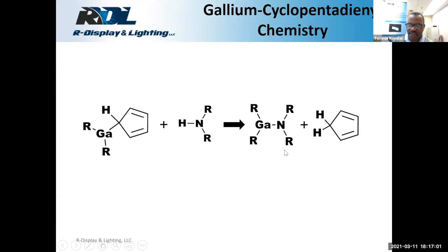In grad school, the interest evolved around using these materials as potential single source or single molecule precursors for preparing ultimately gallium nitride semiconductors. The problem is pyrolyzing these materials ultimately results in incorporating impurities in the microstructure of the gallium nitride semiconductor. So it's not a process that can be competitive with the standard MOCVD process, the bimolecular reaction between trimethylgallium and phosphine or arsine. However, this facile reaction I have found has been very useful in developing other materials with various applications for electronic devices, including OLED devices.